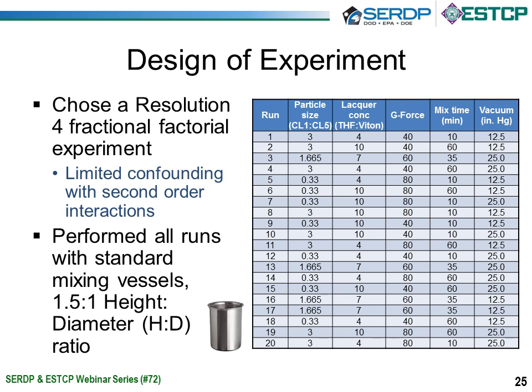We chose this mixing vessel because this height to diameter ratio is what was commonly used for the high viscosity cast cure formulations. We had seen in the past that that height to diameter ratio allowed for efficient mixing of these high solids loaded cast cure formulations, so that's where we decided to start with this research for the pressing powders.